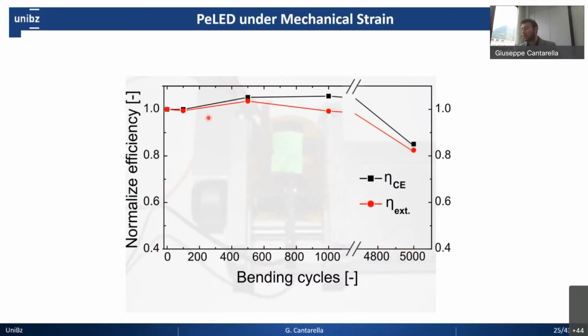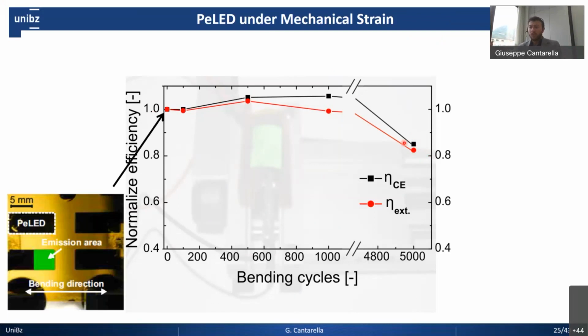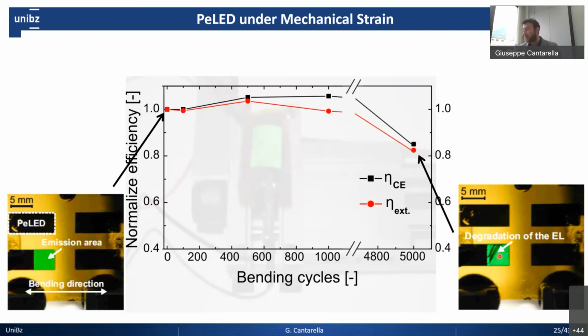And what we did was monitoring the efficiency up to this point. As you can see here, up to 1,000 cycles the efficiency is pretty much stable, and it doesn't change. It's not affected too much even after 4,000 cycles. So reaching this point, clearly due to the exposure to air and the absence of a passivation layer, there is a significant drop of almost 18% that clearly has to be tackled. Just to give you an idea of how the LED looks when it's fresh and starts this kind of test, you perfectly see that the LED is shining green, and the failures after 5,000 cycles are visible with these black lines visible here.